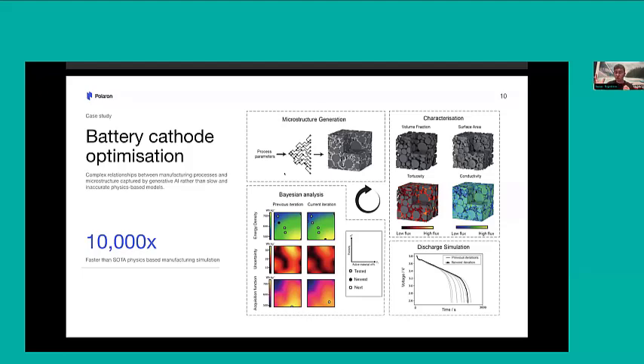And we can generate a structure in under a second, this prediction. If you think about how we would model that with physics, if we were doing molecular dynamics simulations or any type of thermodynamic or finite element model here, that would take a lot longer because we have loads of interacting atoms, but we're learning all of those through machine learning, which allows us to predict in a matter of seconds. And this enables a rapid optimization loop where we predict the structure.